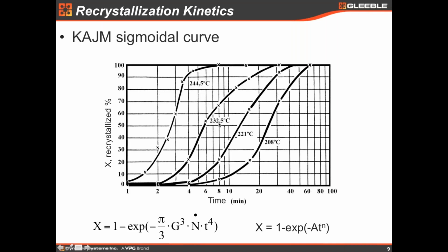We can see here that we have a 12 degrees C difference, and the time to complete recrystallization here, this is aluminum, okay, is 8 minutes, and if you decrease the temperature by 12 degrees, it completes the recrystallization in 30 minutes. So we see that there's a strong effect of temperature, and the temperature actually is not included in this equation here, but it influences the growth rate, that is this G, and this is the nucleation rate, and this is the time. And this is the simplified version of the same equation. Usually when you're modeling, when you're deriving this parameter, you use this shape. Most of the time you don't consider the growth rate and nucleation rate, so you add all that in this parameter here, A. We may come back to that and how to include the temperature in the kinetics equation.